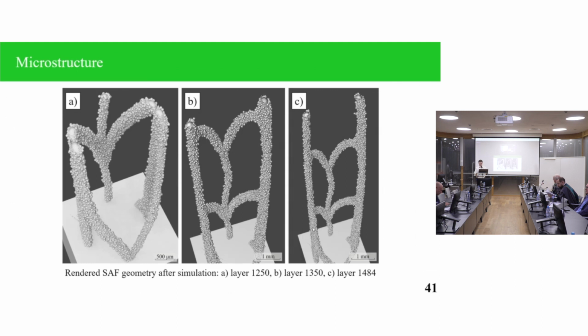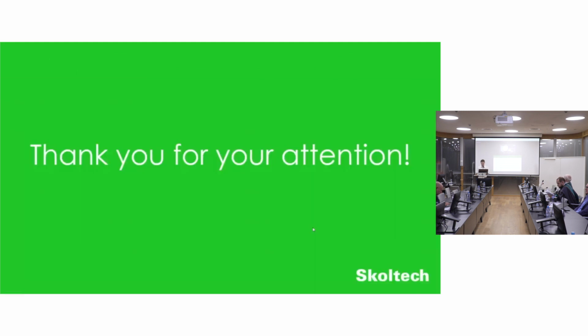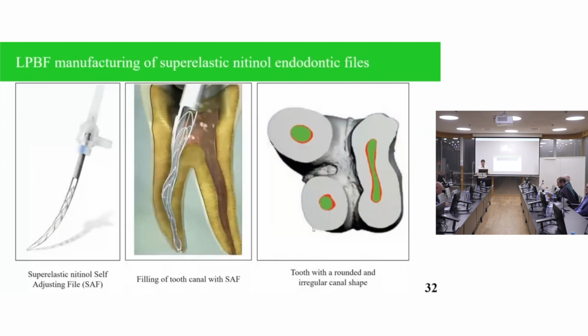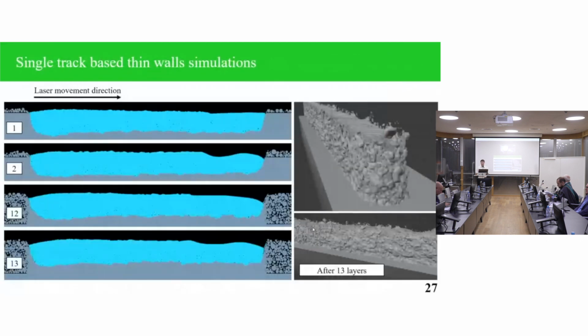What do you think? No, I also need to clarify this. So, as in the case of multi-layer simulation of thin-walled samples, the procedure was completely the same. And actually, the single-track experiment was also performed on the powder layer. So we had powder and then substrate. So for thin-walled simulation, we have powder, then we remelt it, form another layer, and the same procedure was done.